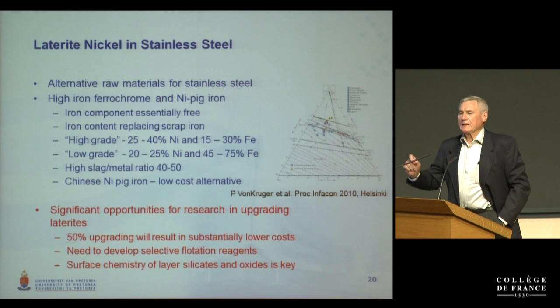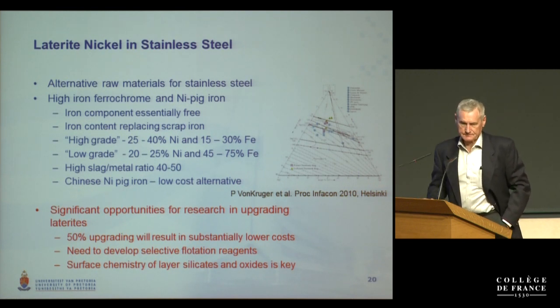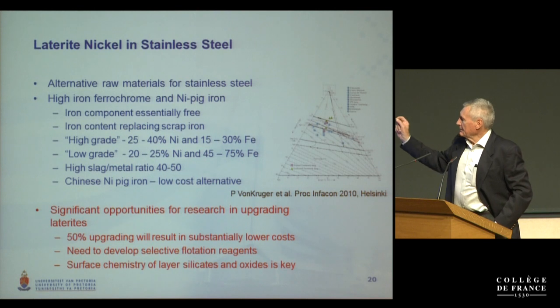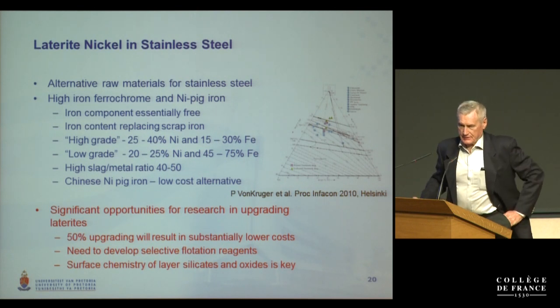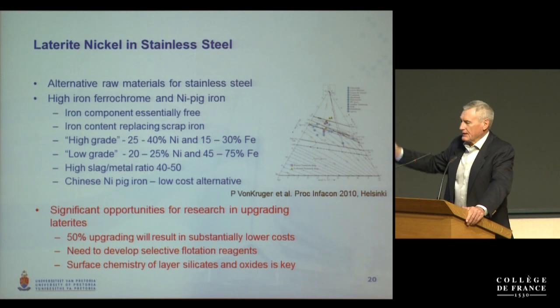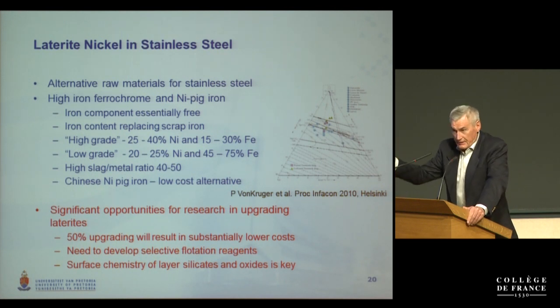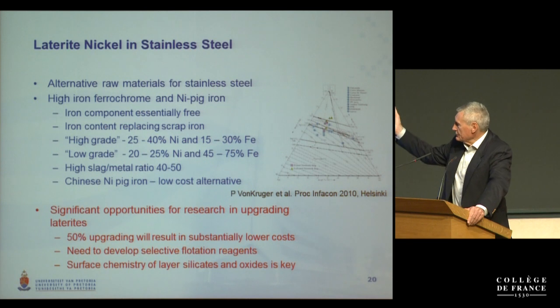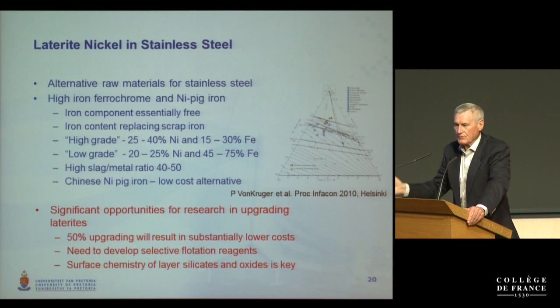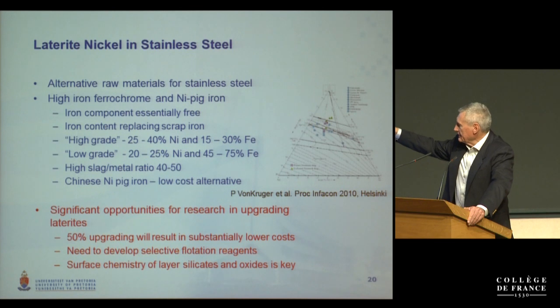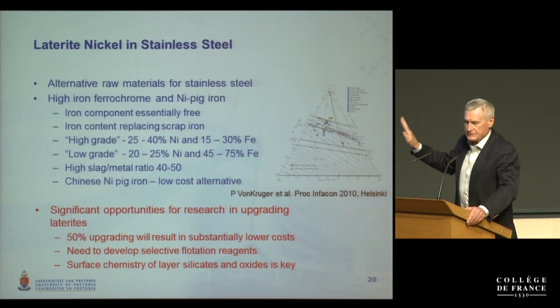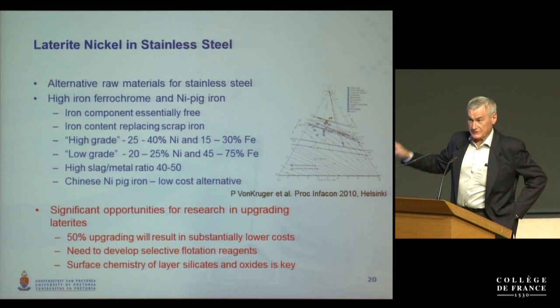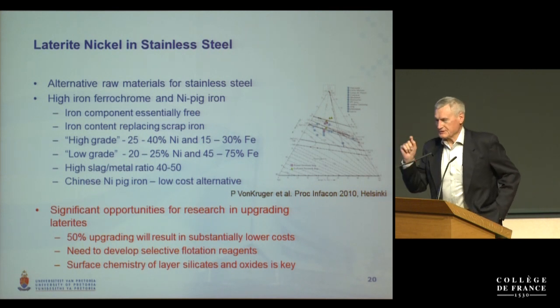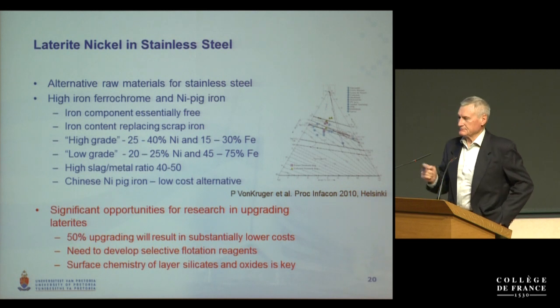but also in trying to upgrade your ore. If one can get a 2 times increase in the grade, and let's say a 50% recovery, you can reduce your slag to metal ratio to half that. You can increase your production. You can double your production just by looking at upgrading of laterites. So I think this is a tremendous opportunity. It's a difficult one, but I think surface chemistry might help us in that regard. Gordon?